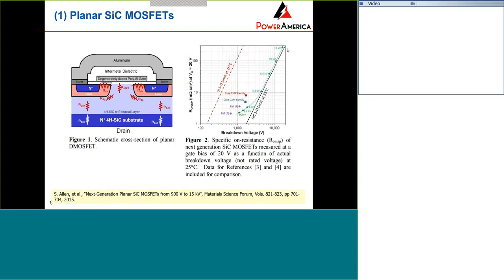So there are low voltage devices coming. But from this figure, you can see that beyond 3.3 kV, the specific on-resistance of all the silicon carbide devices is pretty much identical to the theoretical values because the drift resistance is dominant. When the blocking voltage is reduced, the channel resistance and the substrate resistance become dominant. So you can see that for the 900 volt devices, the on-resistance is still way higher than the theoretical predicted values.